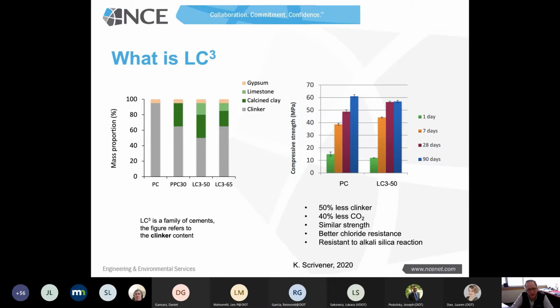So this is really kind of the underlying idea behind LC3. And so we think it's really important to have an LC3 test site in this MnROAD facility, and so we will. And we're shooting for the 50% clinker replacement. Other blends have been made where you have a 30% or a 40% replacement, but we're shooting for a 50% replacement in the LC3.